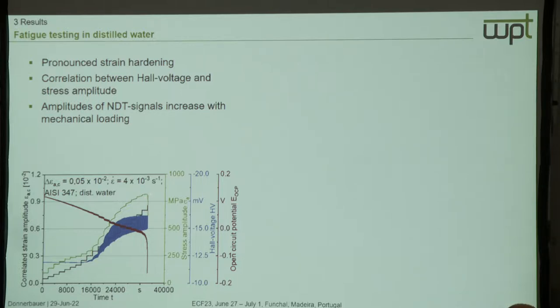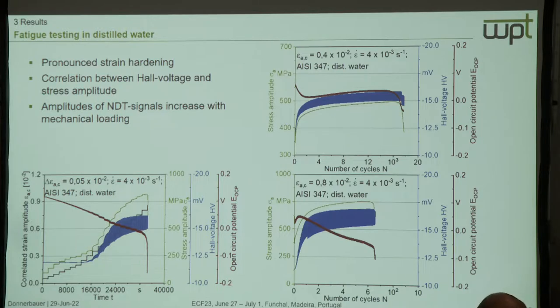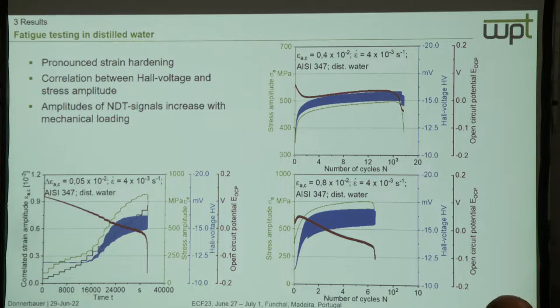The same can be said about the open circuit potential — it appears noisier later but it's the same kind of effect. The open circuit potential shows a sharp drop at the same time as the stress amplitude drop: as the crack propagates, new free surface is created and the potential of the austenitic steel moves to more anodic values, so this can be used to track crack initiation. In the constant amplitude tests, the open circuit potential also shows the sharp drop when the crack starts to propagate.